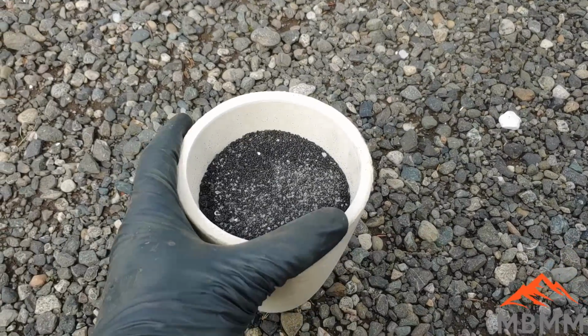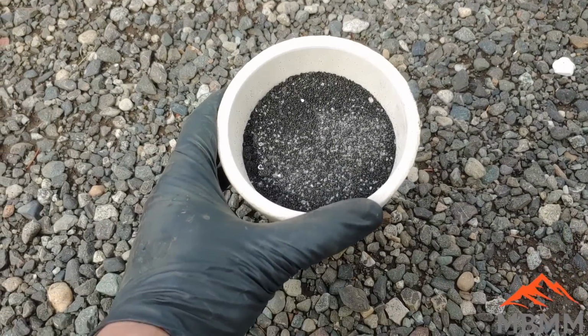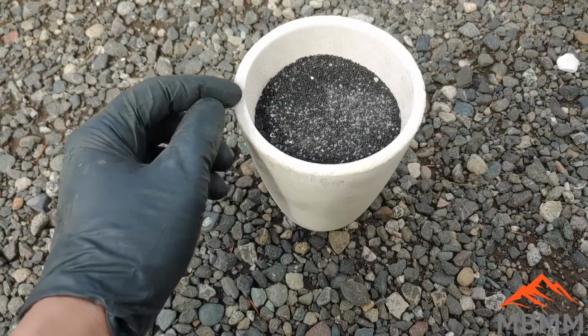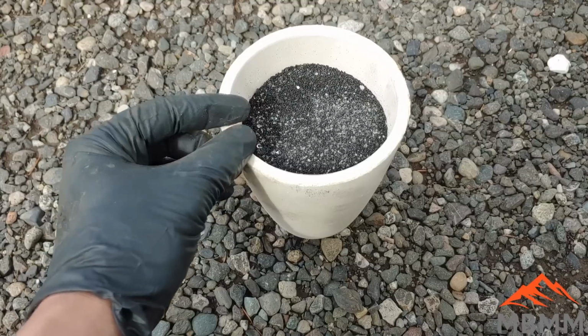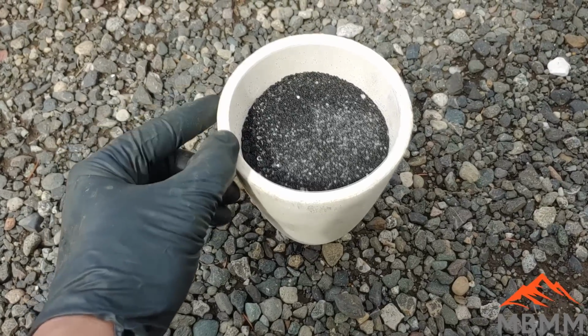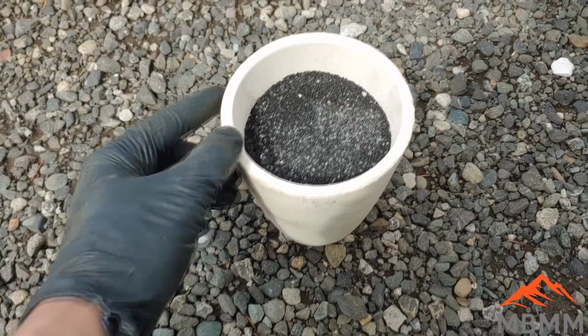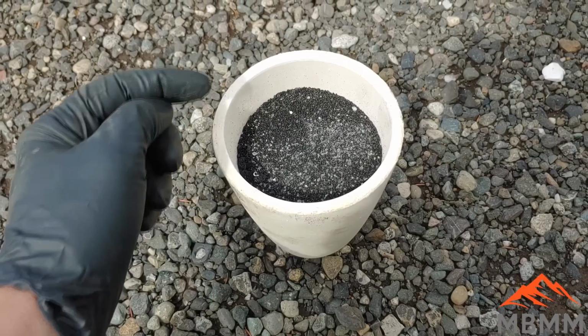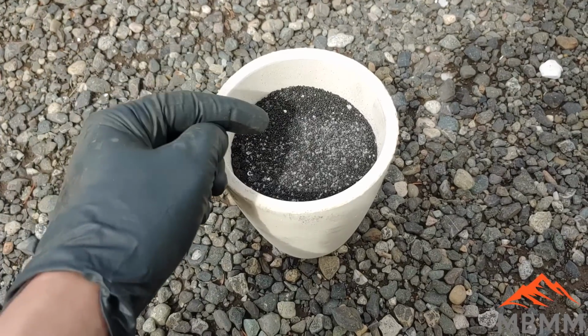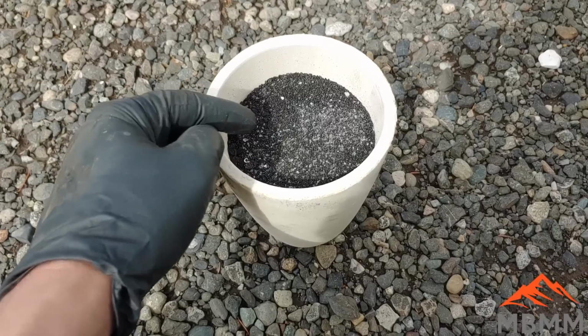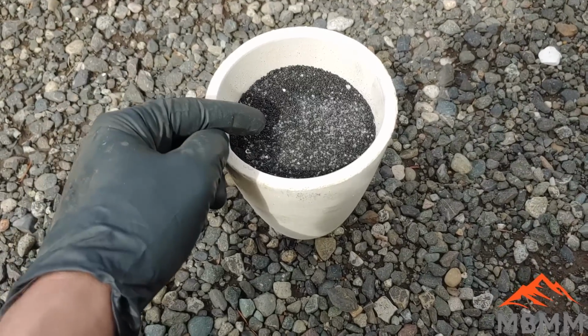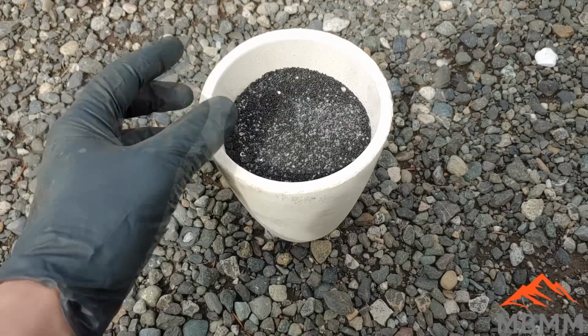All right, guys, here's our next test. This is a little bit different matte. This is all black. I've been saving this separate because this should have mostly lead matte in it. And I'm going to add the iron rod to this, hopefully, which is going to reduce the lead, either sulfide or oxide in here, back to lead metal, create that iron sulfide, and dissolve in the slag.